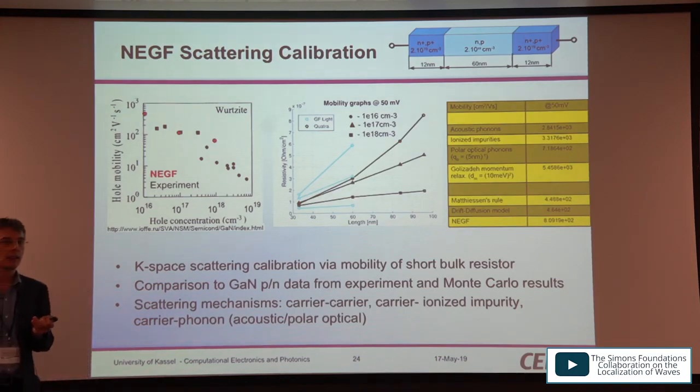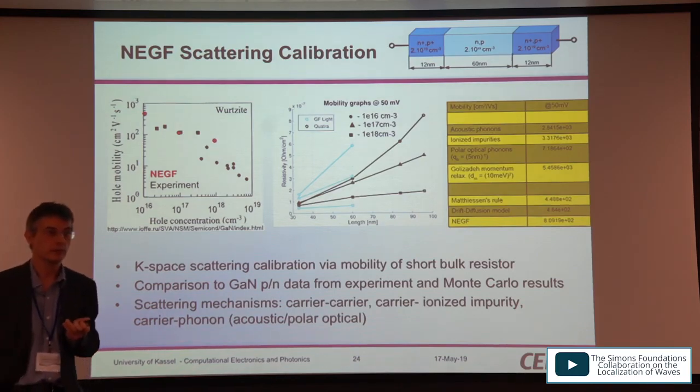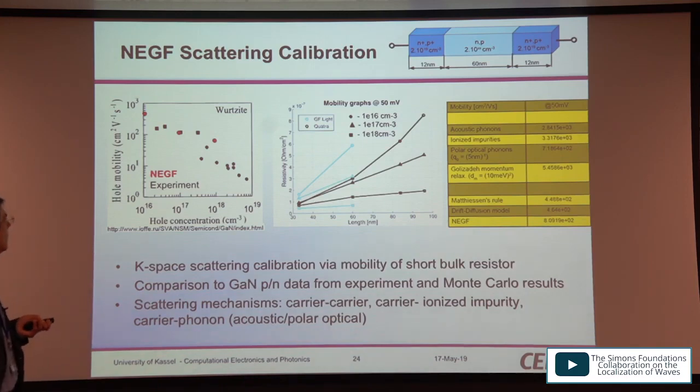What temperature is this? This is room temperature. The low carrier concentration mobility, this one? Well, anything more than about 30 is unbelievable. We got it from there. So maybe it's low temperature. I don't know. Yeah, it's not believable. I think 30 is kind of the highest number that's ever been believable at room temperature.